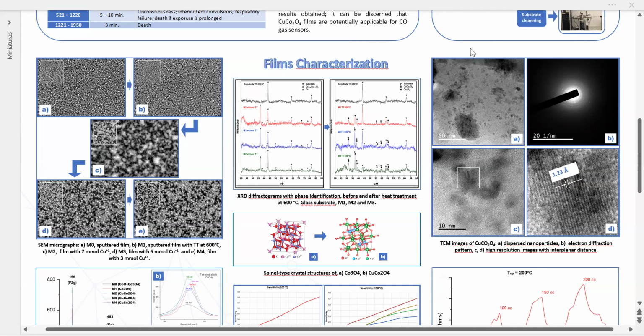The XRD results indicate that the sputtered film with heat treatment was transformed into pure cobalt oxide with cubic structure. In addition, it was determined that the sonochemical process promotes the substitution of copper 2+ ions for cobalt 2+ ions in the spinel-like structure of cobalt oxide, forming non-stoichiometric copper cobaltite before heat treatment to get stoichiometric copper cobaltite, which confirmed the evolution of cobalt oxide to copper cobaltite during the two-step synthesis process.